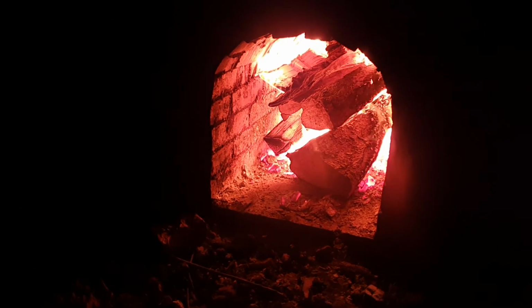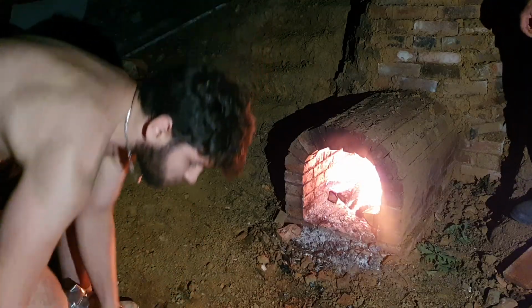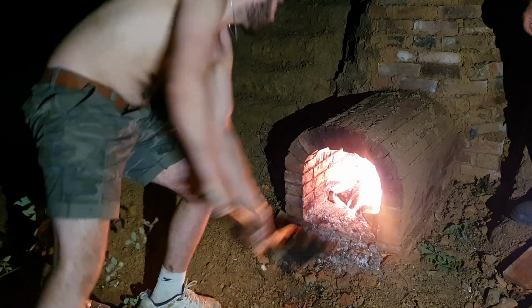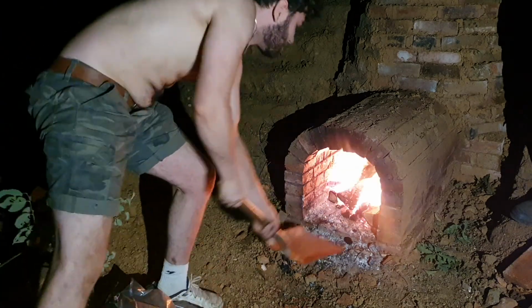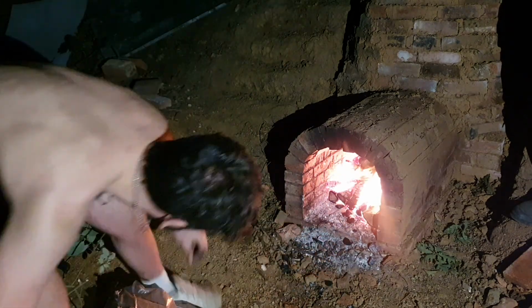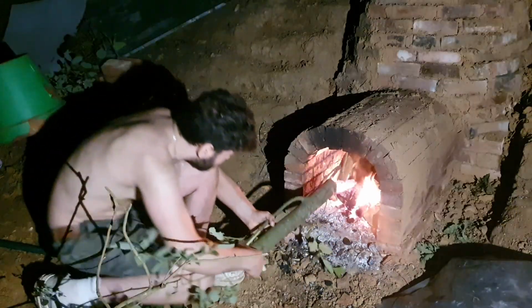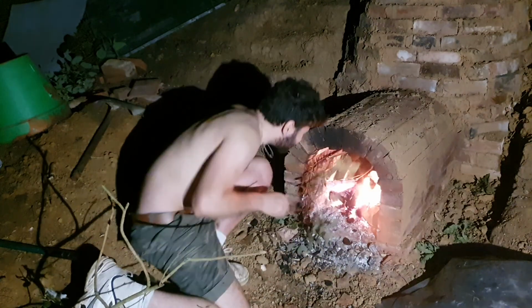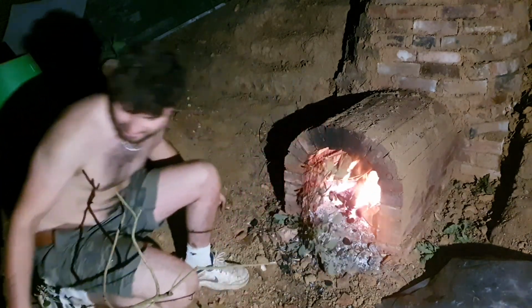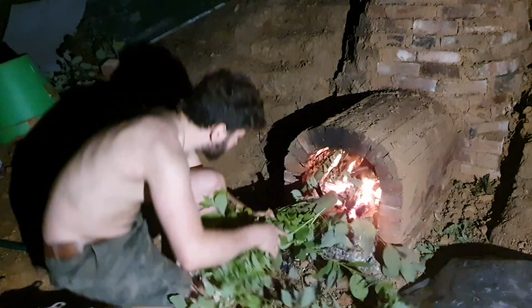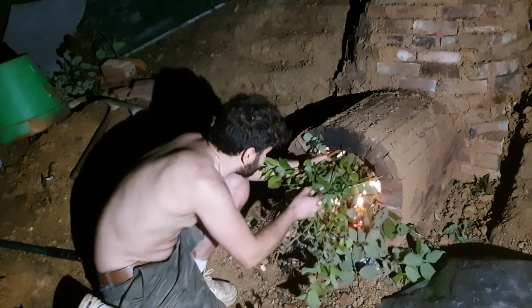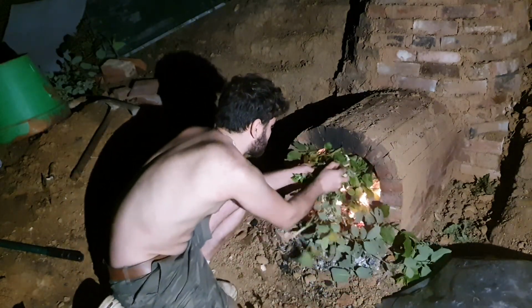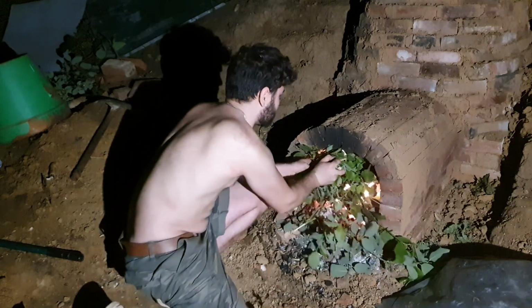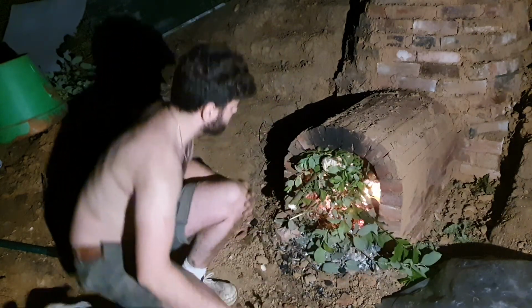With the kiln finally up to temperature, it was now time to start phase 2. I fed the kiln with high carbon fuels, using standard coal to produce smoke and carbon, but also to maintain the temperature of the kiln during the reduction phase. We then used green timber, the moisture content from which would also create smoke and release carbon. It was this carbon that, during the high temperatures of vitrification, I hoped would seal the carbon in and turn the slip black.